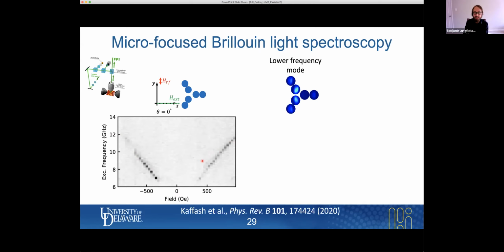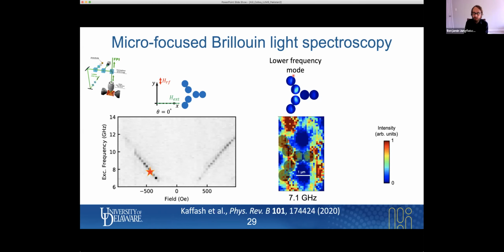And we did this. So let's just remember the low frequency mode was in the oblique elements. And we now perform our BLS measurements. So these are color-coded images where red means a strong spin dynamics signal. The scale bar here is 1 micron. And I'm showing here in gray superimposed one vertex of the lattice. And you can indeed see that most of the dynamics are already residing in these oblique elements.